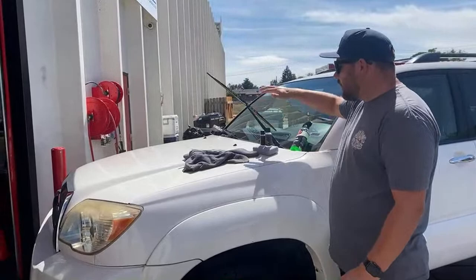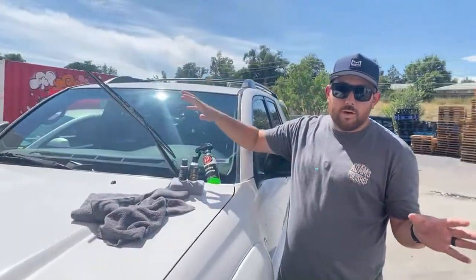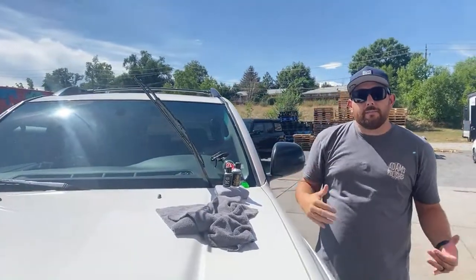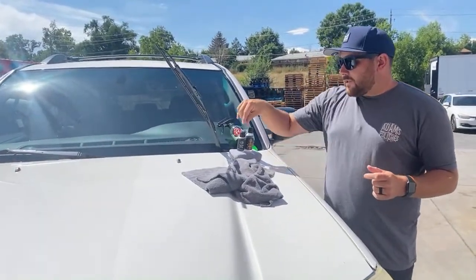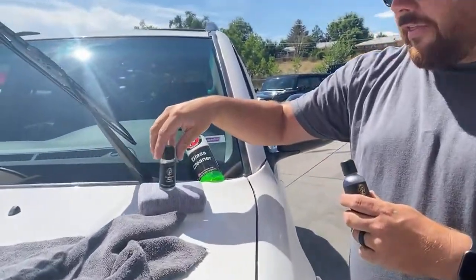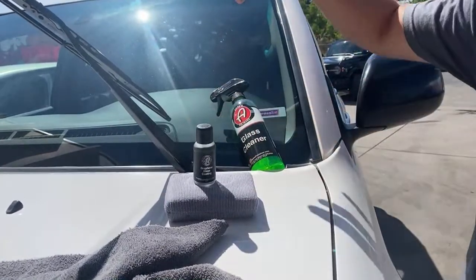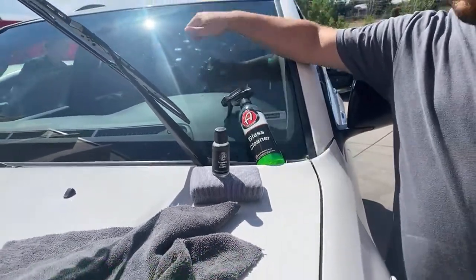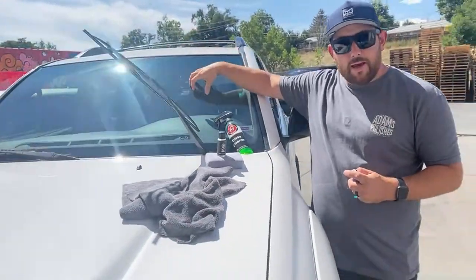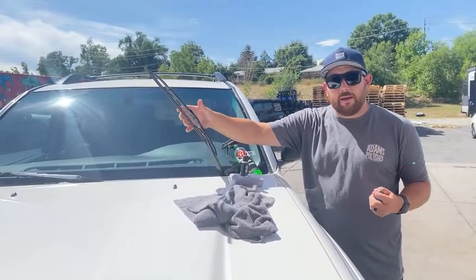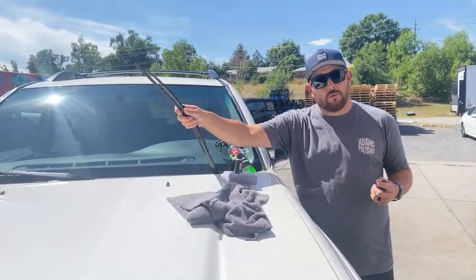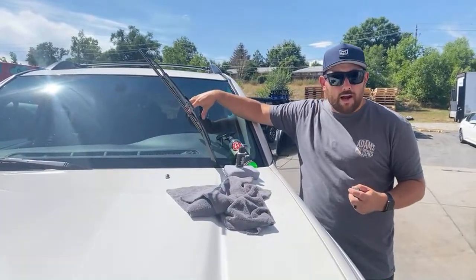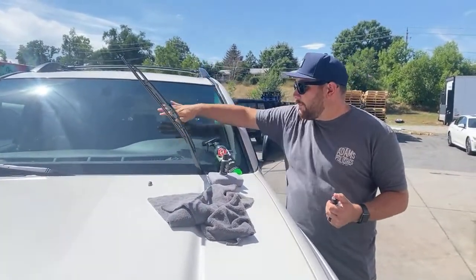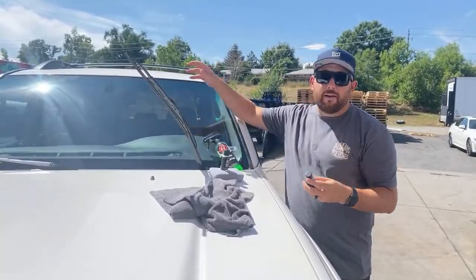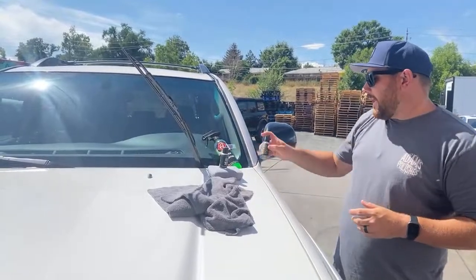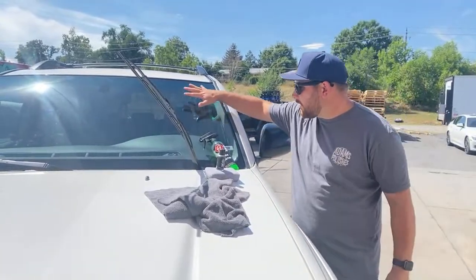So what we learned is the veneer of the graphene ceramic coating on top wasn't the best way to protect glass. So what our chemist Chris Galhar did at B&B Blending was he developed a specific glass coating that is a thinner formula, and a formula that actually penetrates the pores of the glass. And now that it penetrates the pores, it lasts longer, it works better, and maybe the top layer gets abraded away from your windshield wiper blades, but because it has penetrated the pores, it continues to work, and the top veneer of the graphene coating is not just worn away. Now you have graphene glass coating that has infiltrated the pores of the glass and is doing the work to keep it protected.